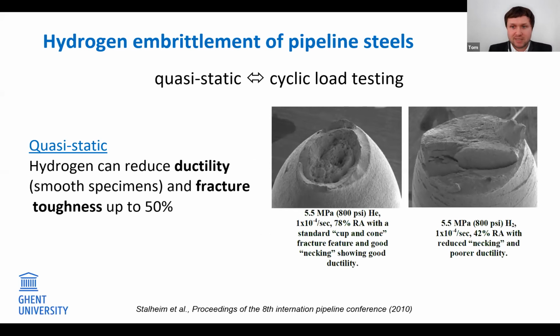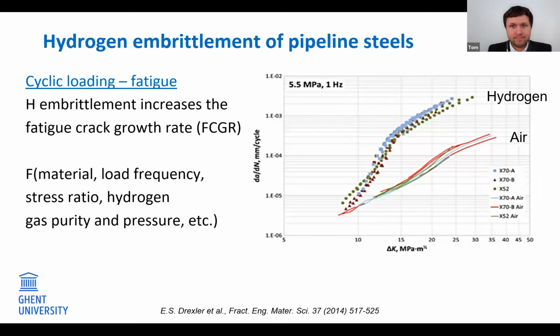The resistance of a material against quasi-static load is described by its mechanical properties. For instance, tensile properties, yield strength, tensile strength, ductility, and also fracture resistance properties like fracture toughness. The ductility of pipeline steel, which is typically expressed in terms of reduction of area at fracture or elongation to fracture, is significantly reduced in the presence of hydrogen. For instance, hydrogen can reduce ductility of smooth specimens and fracture toughness up to 50%. Standard cup and cone fracture features turn towards a reduced necking, as you can see in the microscopy pictures, and poor ductility in the presence of hydrogen. Well, this was with quasi-static. Let's go to the cyclic loading.